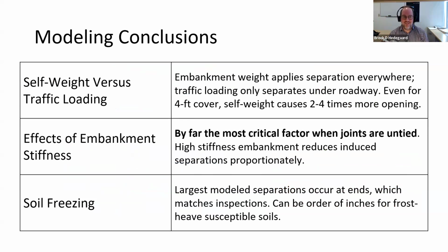So now I can get to the modeling conclusions. In terms of self-weight versus traffic loading, the embankment weight applies separation everywhere. And even for just a modest 4 feet of cover, self-weight causes 2 to 4 times more opening than we see from traffic. So in general, traffic, like I said, is probably a minor player in these. If we look at the effect of the embankment stiffness, this is by far the most critical factor. So if you have a low stiffness embankment, you are probably going to have joint problems.